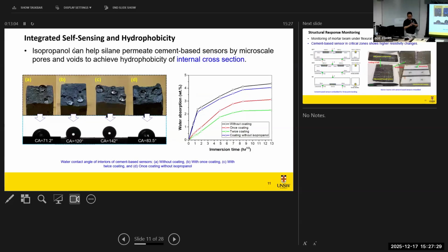And then here, we further look at the internal cross-section of the cement-based sensors. It means we broke the specimen, and then we looked at the water contact angle of the internal cross-section. We found that without coating treatment, the water contact angle is around 70 degrees, as you can see here. After coating treatment, the water contact angles are significantly increased, over 120 degrees. So this means the silane and the isopropanol can work together and penetrate inside the specimen to achieve hydrophobic behaviors. At the same time, the water absorption results also support this point.